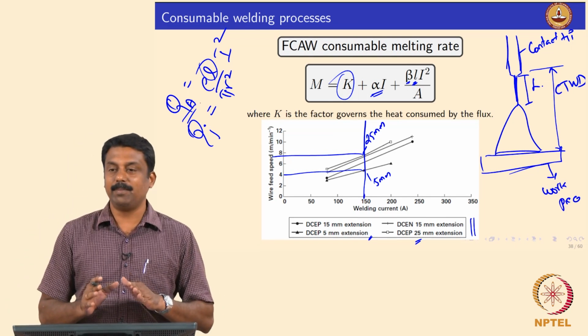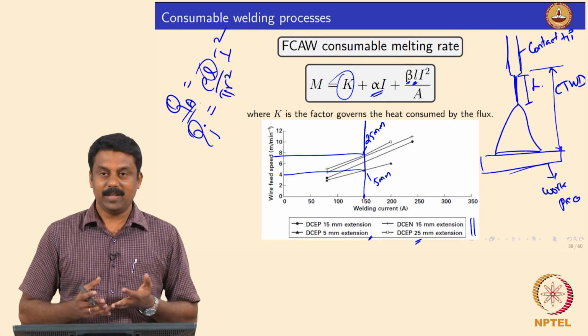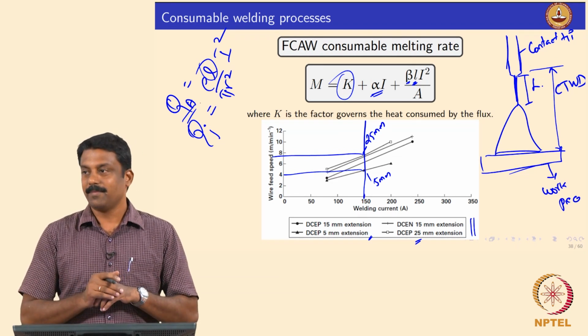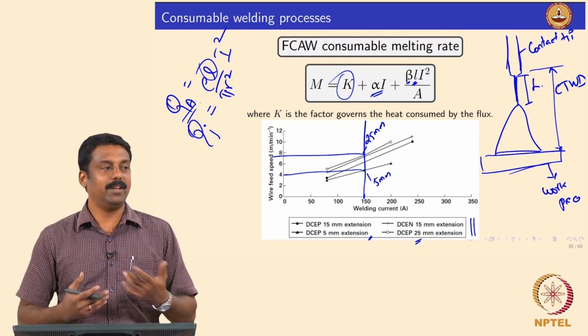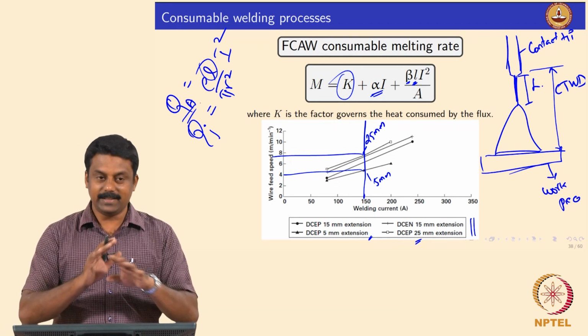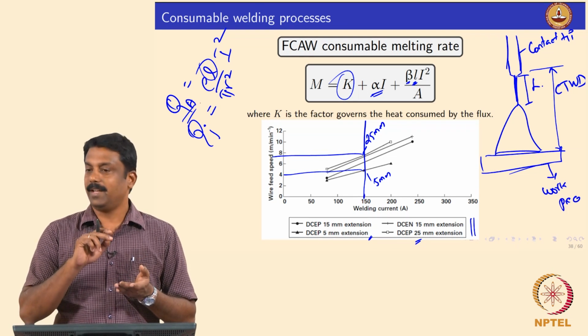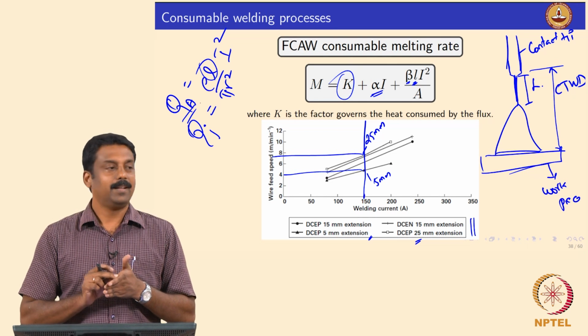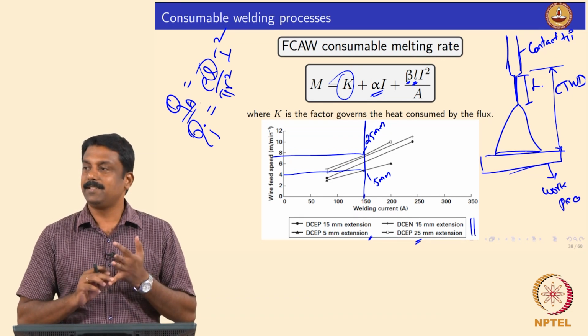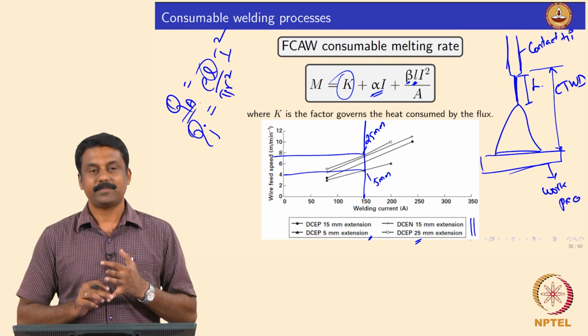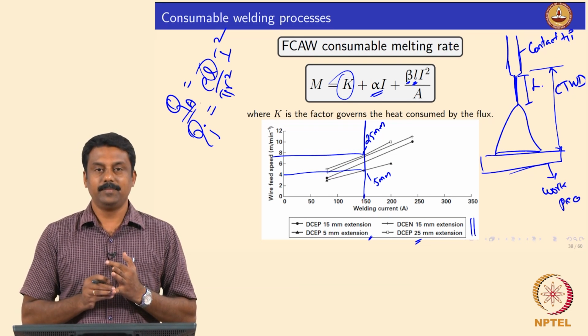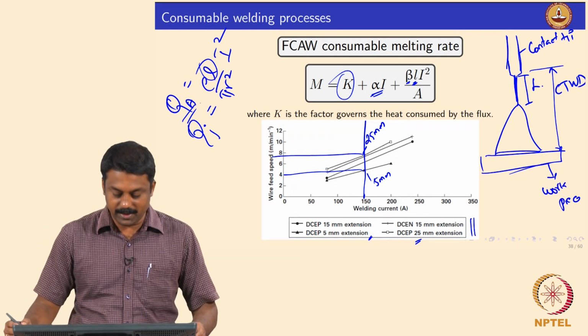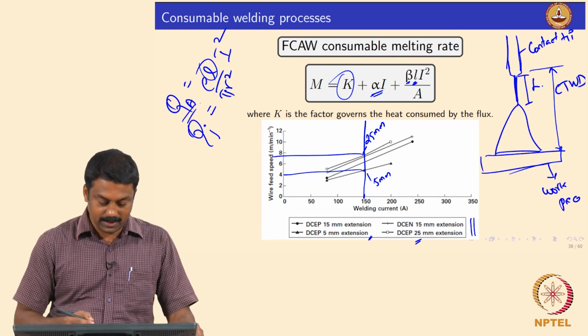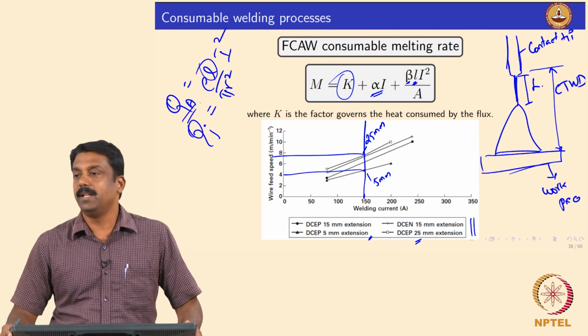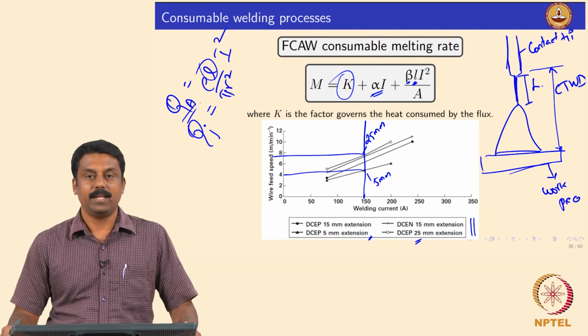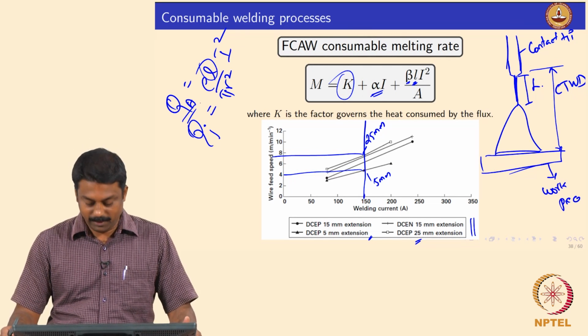That is why it is called independent parameters, because that can also change person to person. So, you weld today morning and next guy comes and welds, and if he changes stick out length, everything is the same, shielding is same, the process is the same, material is the same, diameter is the same. Even if you fix the current, if you change the stick out length, then melting rate changes, right, it is clear. So, this graph shows in FCAW by changing the stick out length, you can almost double the melting rate. Yes, it is clear. Okay, good.